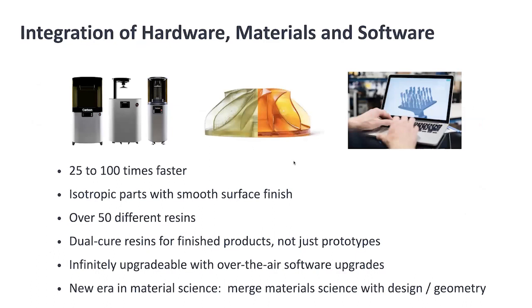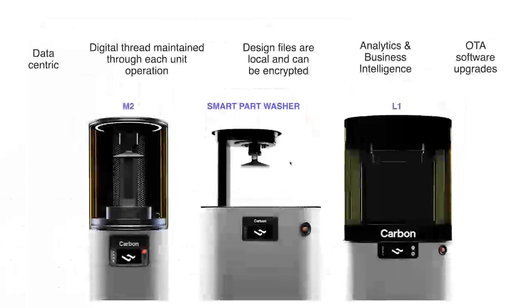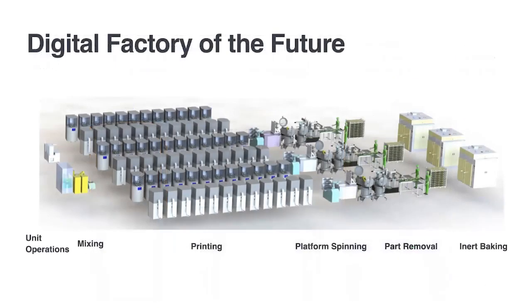And so what's happening is that we now have a process that's really fast. They're isotropic parts. We have lots of different resins, and this sets you up for moving into manufacturing, and that's what we do. And so this idea of putting those printers together into a mini factory, where you now are not just thinking about the printing, but now you've got to mix resin at large scales, 1,000-liter totes, for example. You've got to print the part, but because of the part printing, we have excess resin on the parts. And historically, we've always just washed that in organic solvent, and that's convenient at low volumes, but that's not convenient at the million scale.